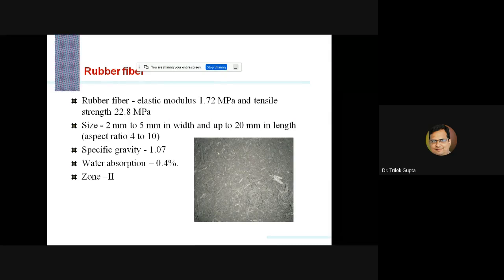Another form of this waste rubber tire used in this study was the rubber fibers. Specific gravity was 1.07 and water absorption was 0.4%. They were made from the same waste rubber tires, but obtained by mechanical grinding. To obtain the rubber ash we use the pyrolysis technique, but to obtain these rubber fibers, we simply use mechanical grinding of the waste rubber.